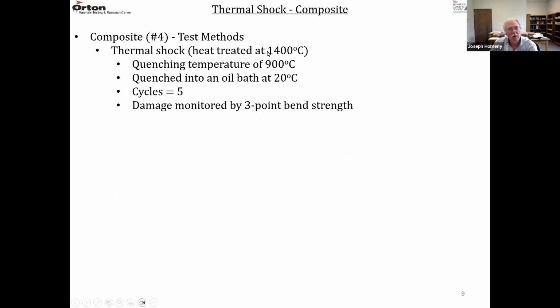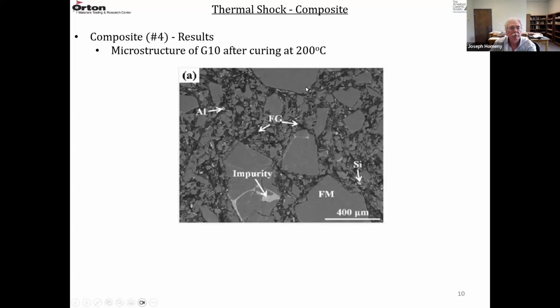The thermal shock was done on the composite samples at 1400 C. 900 degrees C was the quenching temperature, and then it was quenched into an oil bath at 20 degrees C. They ran 5 cycles and used the 3-point bending to monitor the damage.